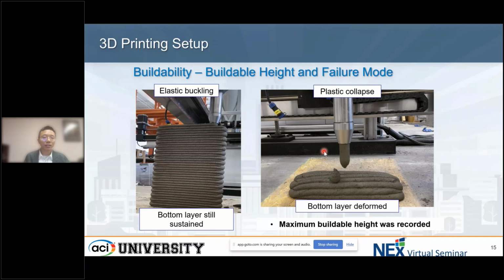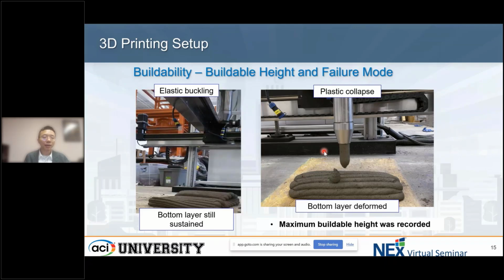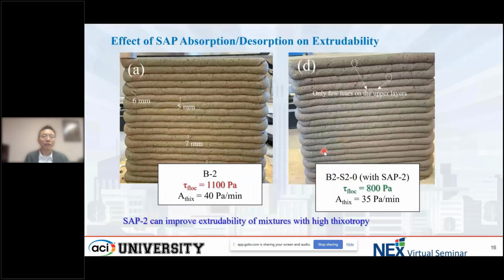Because we print a single layer, when elastic buckling happens, it means it has very good thixotropy property. And in this case, the bottom layer still can sustain its shape. And then, first we investigate the effect of SAP on the printability. We evaluate the printability based on the surface quality.